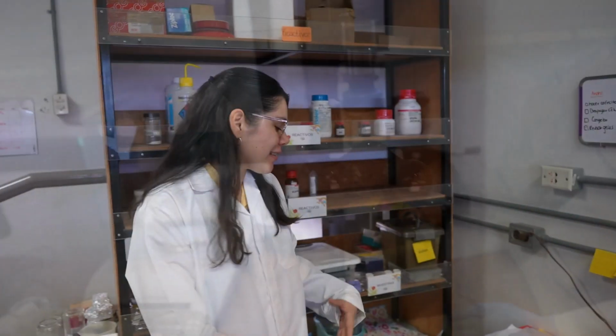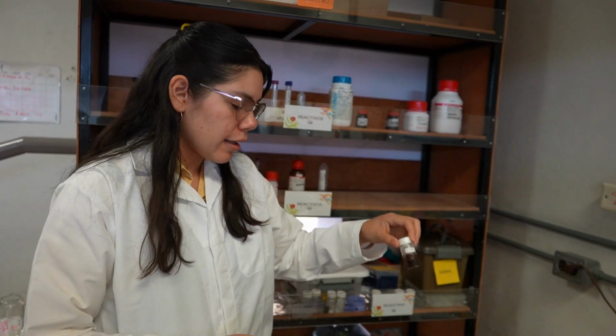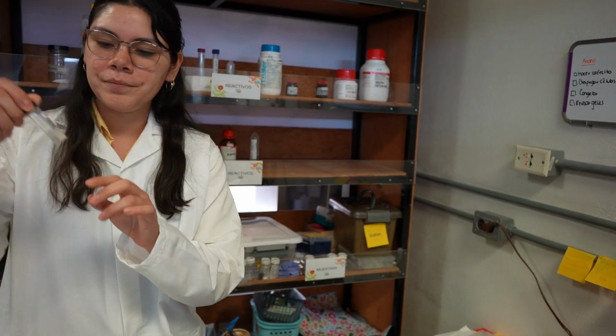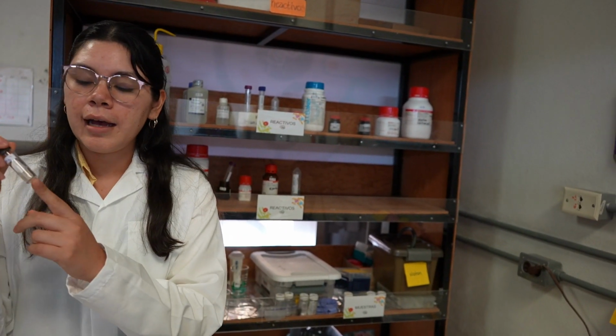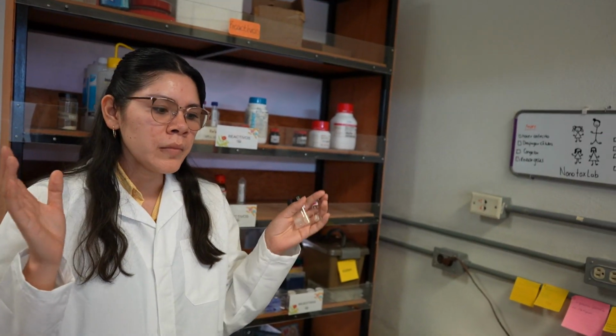The design of hydrogels too as scaffolds, with gold nanoparticles as spheres and rods. Look here, I have nanoparticles in spherical form, and here some gold nanorods. These two materials I embed in the synthesis of the hydrogels, and it looks like this. This is my hydrogel. Then I put this to dry for some days, and it looks like this. Now I can cut some slices and put them on the cell culture plate, put some cells on the surface, and see if it has adhesive properties, so these cells can grow on the surface.